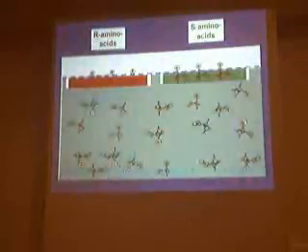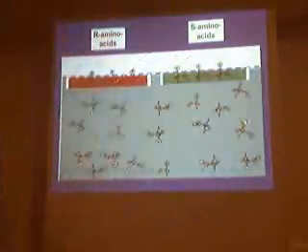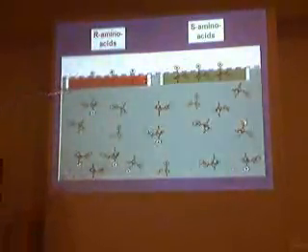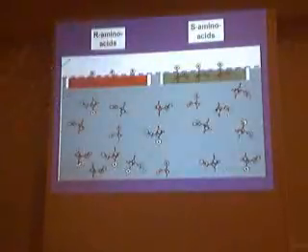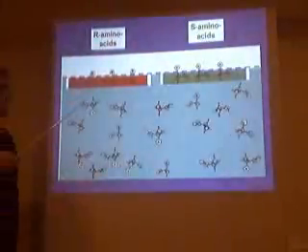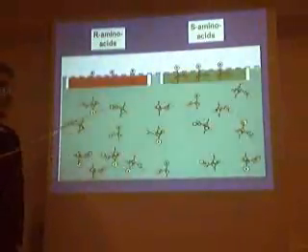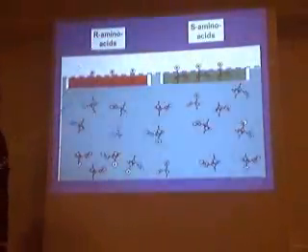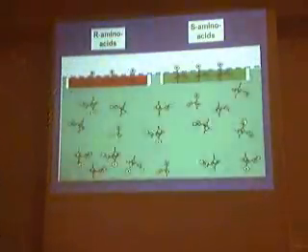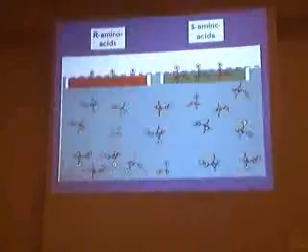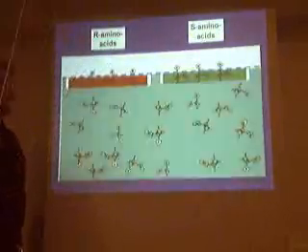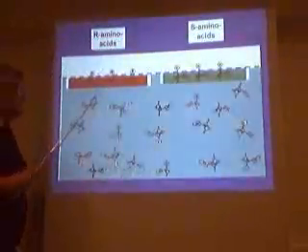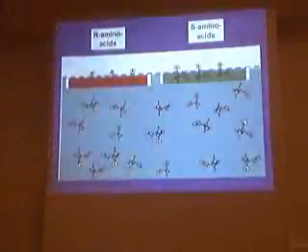Okay? You see that because of the packing arrangement, if you look at the crystal structures, valine, leucine, all of them have heterionic layers, which form single homochiral layers in the water interface, including the racemic valine, leucine, and all these amphiphilic molecules. So what we were proposing was that when we have molecules in solution, the amphiphilic molecules are in equilibrium with the air-water interface. But when they reside at the air-water interface, they constitute a cluster. And the polar head groups of these clusters are appropriately aligned for the induced nucleation of glycine starting from one of the surfaces.